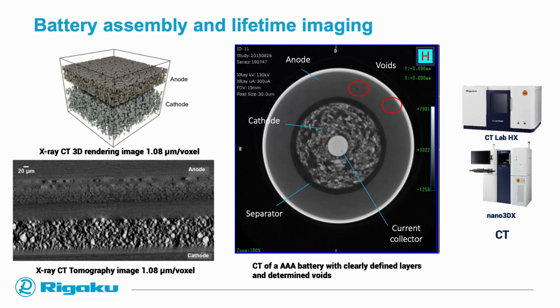For that, we simply use X-rays, and we use the absorption and the transmission of our X-ray radiation. For example, in this case, the anode and cathode material are clearly visible. On the other side, voids and holes inside the battery are visible as black holes. And for this purpose, you would need a CT lab HX or a Nano 3DX. With the help of the CT, you are able to clearly identify the different structural layers of the battery. And this one is, of course, a non-destructive way to analyze established battery cell.